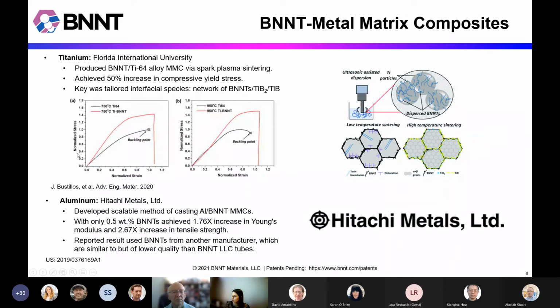And then he explored different sintering temperatures. So here is a stress strain curve of a lower temp and a higher temp sintering process. And he saw that the higher temp process actually gave him better results. And they attributed that to the presence of some of these decomp byproducts at the grain interface, but that actually was what helped the bonding of the tubes to the Ti64. So that's some recent work out of there in 2020.